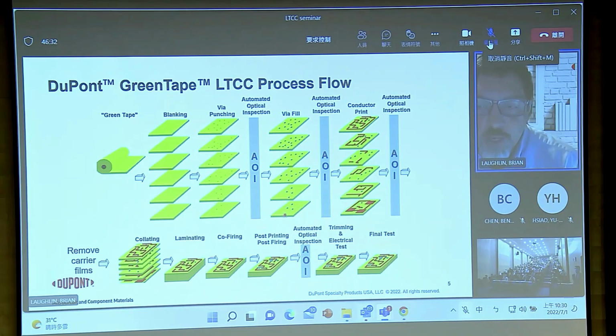You can then do a via fill. You provide a place for that. I'll show that in a couple of minutes. Again, inspect to make sure there are no defects at this point. You can do the conductor print. That's then going to be the XY plane of all the circuits. And then collate precisely all of the high quality layers that you've made for registry, and then go through the lamination step and the firing step.